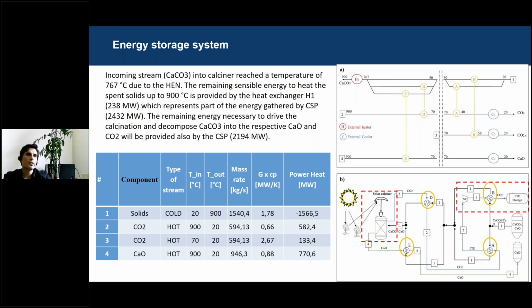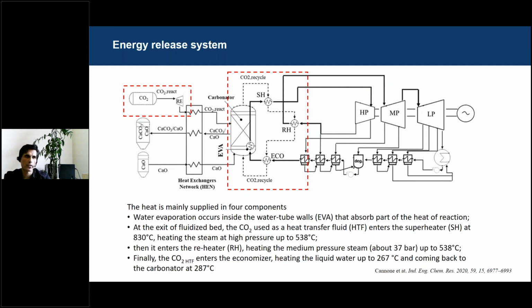We have highlighted in particular 3 hot streams, which are the CO2 released in the calciner, the calcium oxide produced in the calciner, and the CO2 leaving the storage compressor. The only key cold stream is the calcium carbonate, which feeds the calciner. Similar approach also for the energy release area. This is composed of the carbonator, which releases the heat, and the CO2 storage tank, where the energy can be recovered by a train of turbines, so we can recover part of the compressor work.